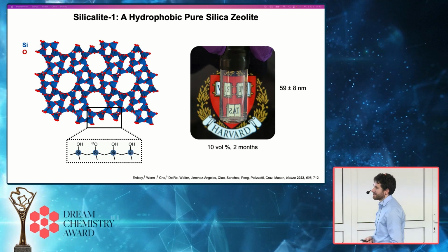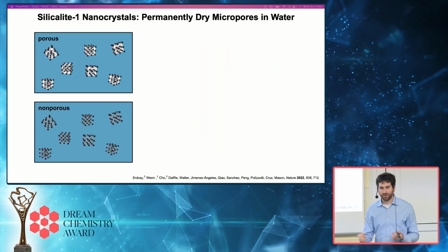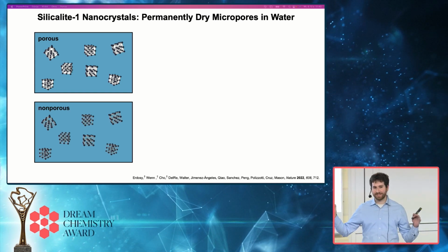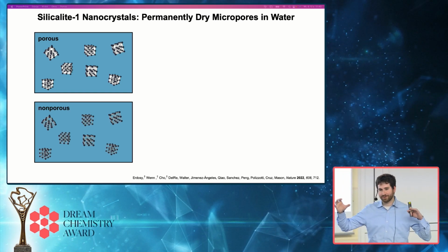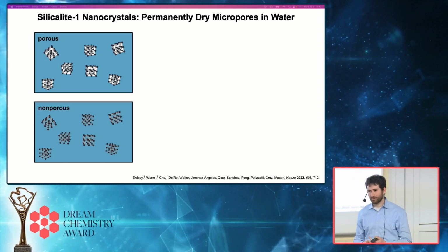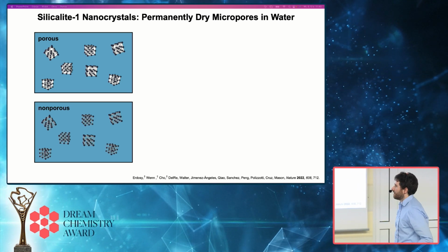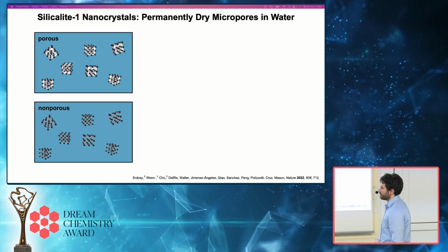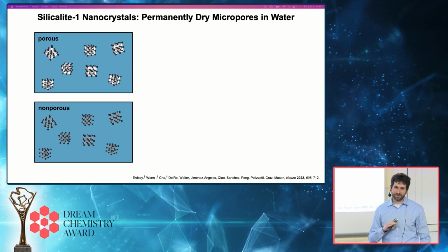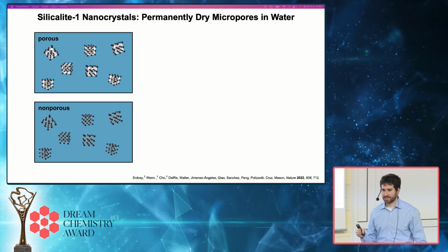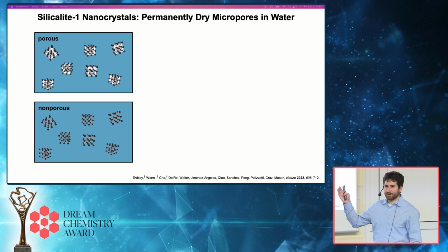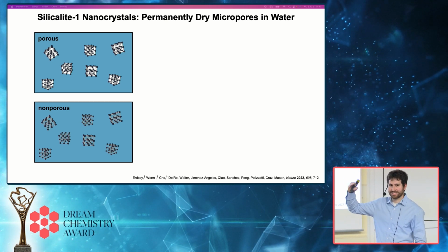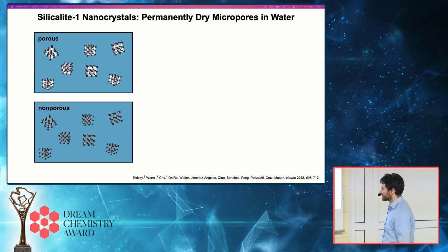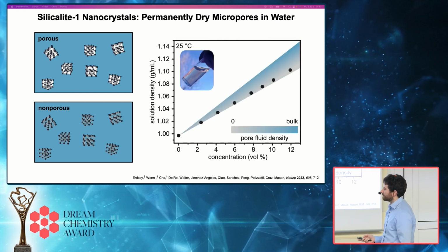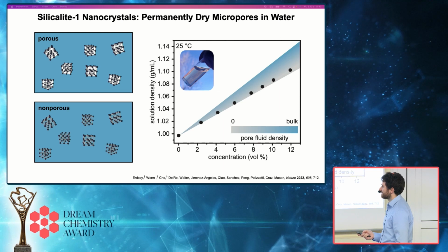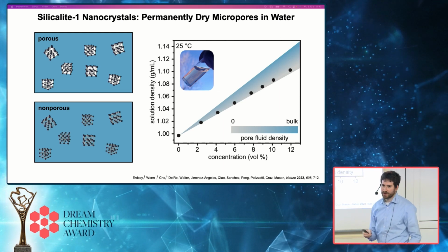So the first thing we wanted to do is to actually convince ourselves that in these solutions that look like water, we actually can have 5 or 10% empty space, and that the pores of these zeolite nanoparticles, even when you're in a nanocrystal that's surrounded by water, actually do remain completely dry. And so the way we did that initially was just by a relatively simple experiment where we looked at the density of these dispersions as a function of concentration, and the density of a solution that contains nanoparticles with water-filled pores is going to be higher than the density of a solution that contains air-filled or dry pores. And so what we found is that in our Silicalite 1 dispersions, we see densities that are very consistent with what we would predict for completely dry pores.